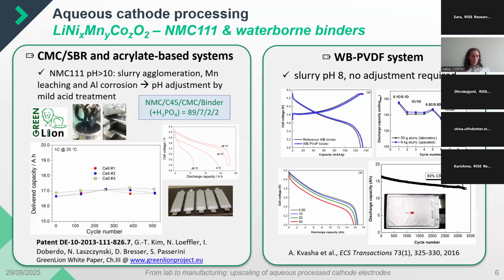So there was this work in which we also collaborated at the time of an FP6 European project called Green Lion that led to a patent, a German patent deposited by the University of Münster, on using phosphoric acid as a pH buffer to regulate this pH and keep it around 9 and not higher than that, to avoid aluminum corrosion.